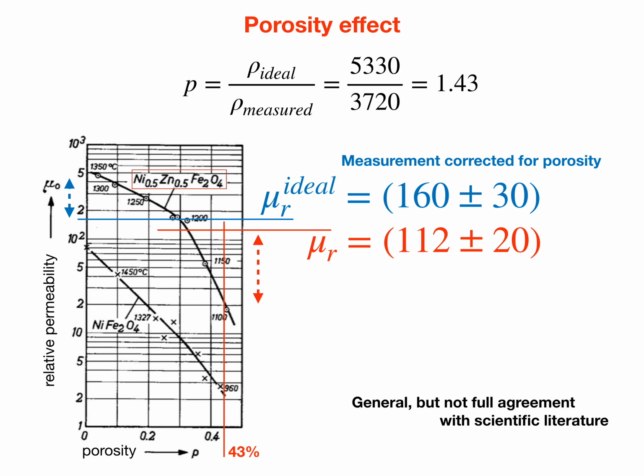It is well known that ferrites such as the nickel-zinc ferrite, for which results were obtained, are affected considerably by porosity. This can be explored by weighing. A typical result is shown here. Assuming a density of 5,330 kilograms per cubic meter for homogeneous material, measurement gives an actual density of 3,720 kilograms per cubic meter. The porosity is therefore about 43%.